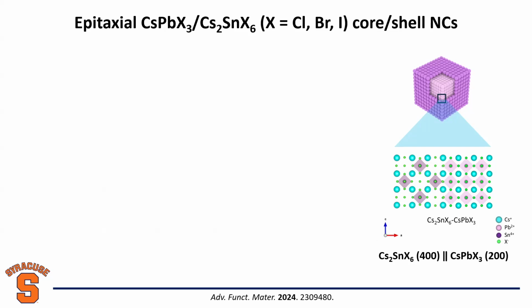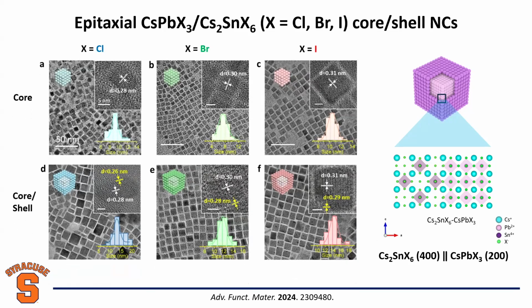But if you look at the arrangement of the halides, the small halides, they are identical arrangements between double perovskite and perovskite. If you look at the cesium arrangement, the big blue spheres, they are identical. So if you calculate lattice mismatch based on halide and cesium, it is very small, less than 10%. So we thought we might be able to do it. Definitely, hand in the back worked on the project for a year, and I'll just give you the final results.